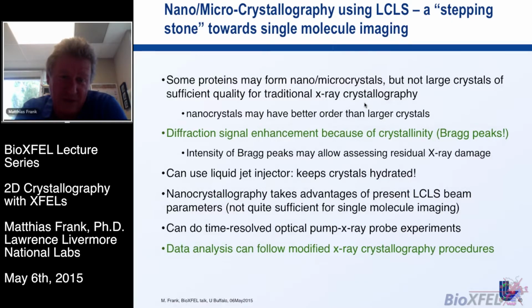But it's nice that you're actually dealing with a micro or nano object, and nanocrystals as small as maybe 200 by 200 nanometers have been measured. But because they're crystalline, you have the Bragg reflections, you have the enhancement of the signal in the Bragg peaks rather than just a low signal-to-noise diffraction pattern.